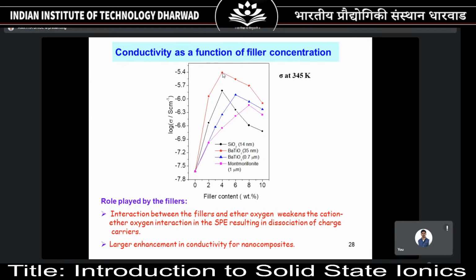That's the role of composites, or the effect of adding fillers. And again, you could see that nano fillers have enhanced the conductivity drastically. This is submicron size. Still, it is very high compared to your host matrix. And when you have used nanometer scale particles, it has reached up to roughly -5.4, and that is the conductivity of the polymer electrolyte.